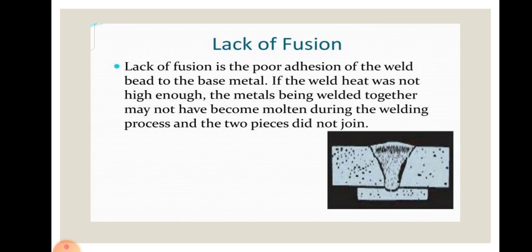The causes are large arc length, fast arc travel speed, electrode diameter that is too large, and current that is too low. To improve this, we should use short arc length, slower arc travel speed, small diameter electrodes, and maintain proper electrode position to remove this type of welding defect.